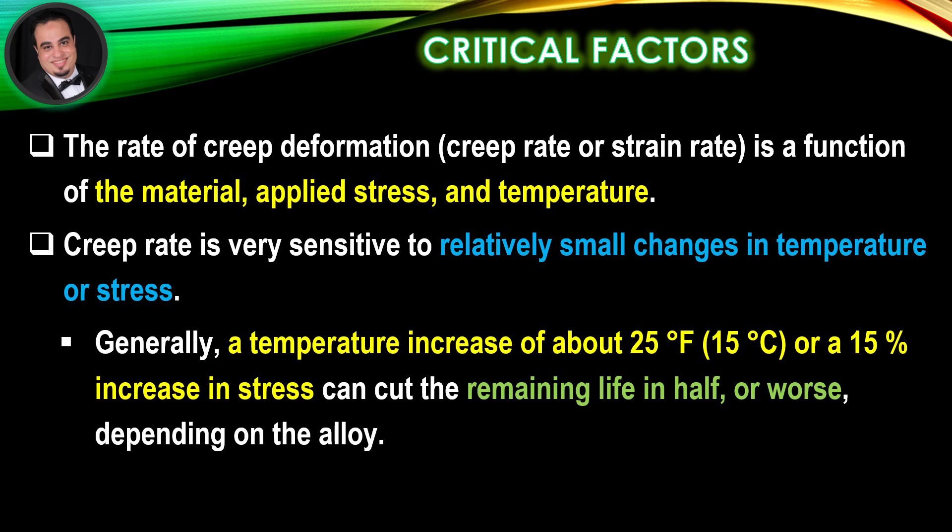Creep rate is very sensitive to relatively small changes in temperature or stress. Generally, a temperature increase of about 25°F (15°C), or a 15% increase in stress, can cut the remaining life in half — or worse — depending on the alloy.